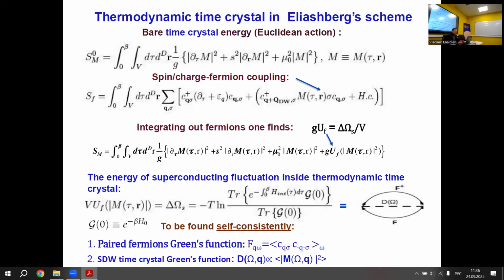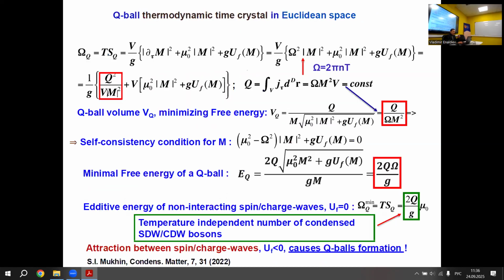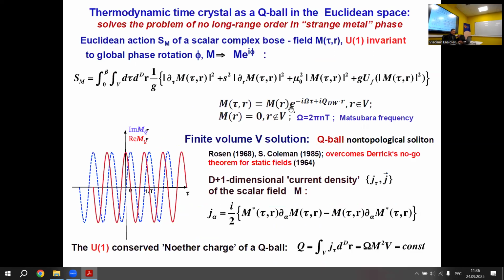This is very important because what is considered here is that this charge or spin density wave has some preferential wave vector. So this is either single charge or single spin density wave. And we shall see where this preferential single wave vector comes from. It comes from nesting of the Fermi surface because it is known that in cuprates there are so-called anti-nodal points on the Fermi surface, and we consider that they are nested by this Q vector. So this is nesting vector.